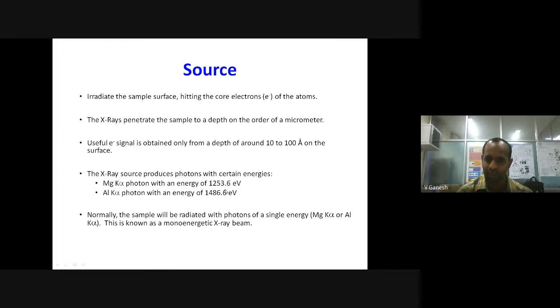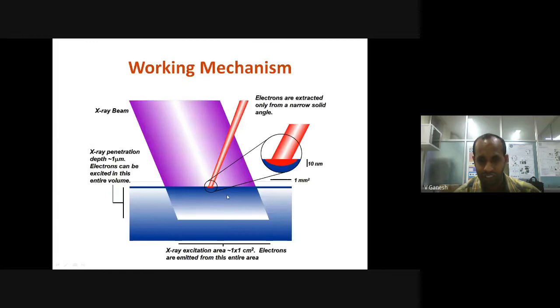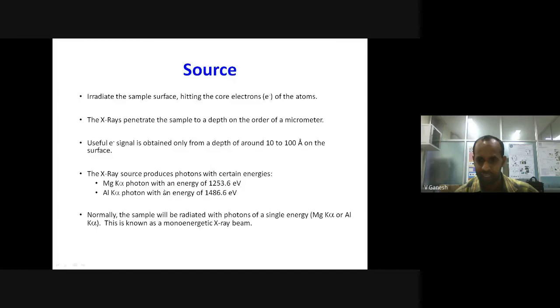Similarly, most of the equipment use what is called aluminium K alpha as an X-ray source. The aluminium K alpha radiation is of the order of 1486.6 eV. This is the value you would use as a photon energy in the previous one. So that's where the source becomes very critical.